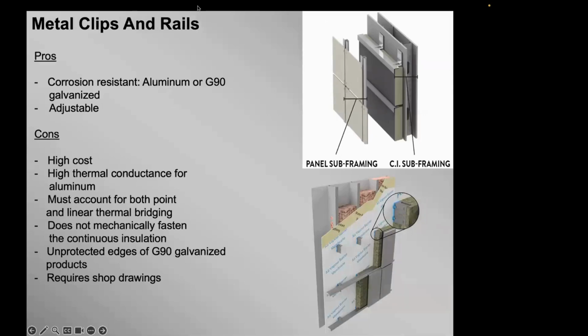So then you have metal clips and rails. There's aluminum or G90 galvanized. They're very corrosion resistant, both of them. There's some adjustability built into these, but as you can see, it's two parts. So you have to do a psi value for the clips or a psi value for the rail, the attachment rail, and a chi value for the clips. It's a complicated calculation for that.